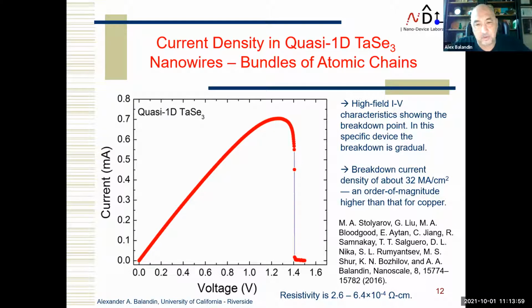The first property which we introduced, and I think that brought some extra interest to this field, is that they can have very high breakdown current density. In the first experiments we did in 2015, 2016, with quasi-1D tantalum triselenide, we measured the cross-section area accurately with AFM, and you can see that the breakdown current density could be up to 32 mega amperes per square centimeter, which is an order of magnitude higher than that of copper measured by the same DC stress. And of course, they have a higher resistivity than elemental metals. However, other groups have also now shown that the scaling of resistivity in van der Waals materials is very different.